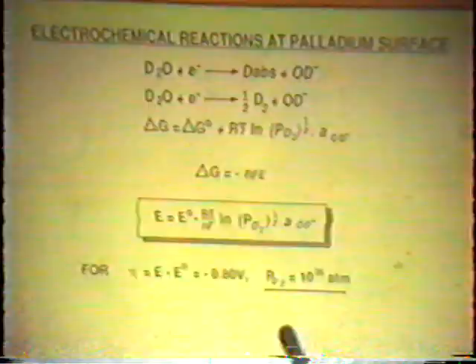The original paper by Fleischmann and Pons used this figure. That's where I got it. But it's not real pressure. It's effective pressure. It's like activity in solution. The right word for it would be fugacity in the gas phase. It's really a fugacity. But it is a tremendous driving force that drives the deuterons into the palladium.